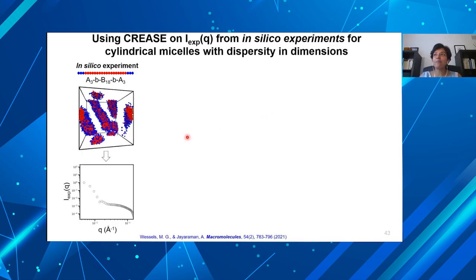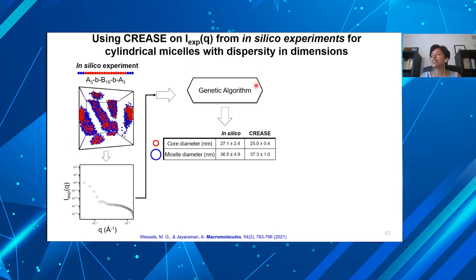Similarly, we did the same, but in this case, now we moved to cylinders, and this is an in silico experiment, so we know the right answer already. And so we tested that with CREASE. So here are cylinders with dispersed dimensions. And when we applied CREASE, our dimensions for the cylinders are within the standard deviation of the in silico cylinder diameter and core diameter. So these are the answers we knew in this case because it was an in silico experiment.